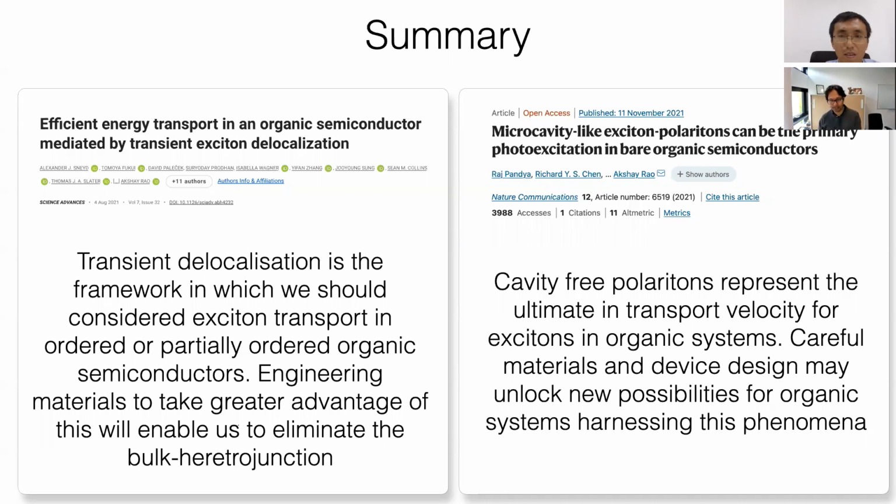So if you're talking about photostability, there are different aspects to it. What you want is to avoid excitons finding each other. But this can be tricky. You need to make sure your coupling is such that excitons can't move, but charges can move in an OFET. But I would suggest that in an OFET, since you don't want to interact with light, it's easier to just have some other layer there which absorbs the high energy photons, and a lot of these materials are already available. In an OPV, of course, it's more challenging because you need to absorb all the light. And there, our best option is to move the excitons as quickly as possible and dissociate them.